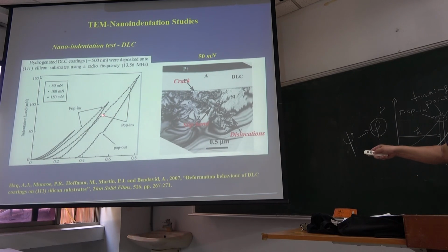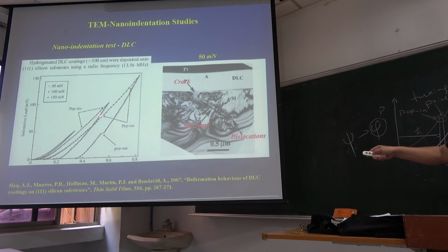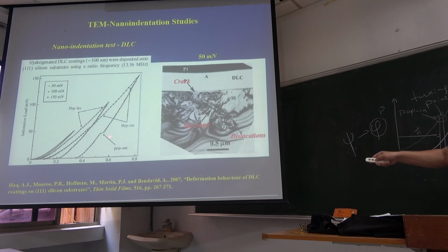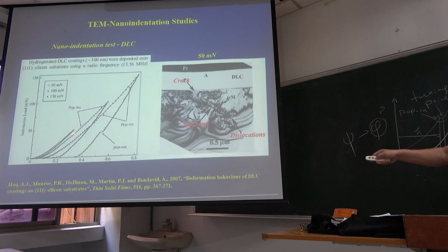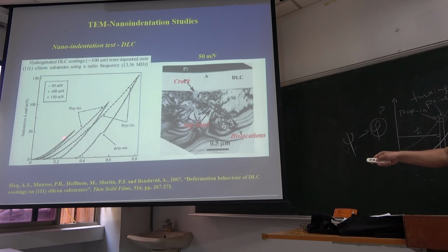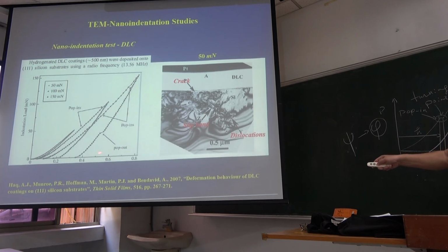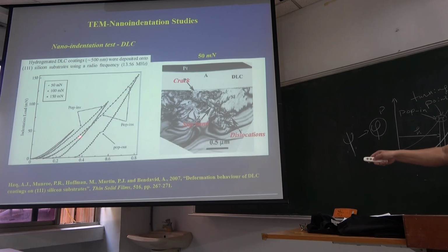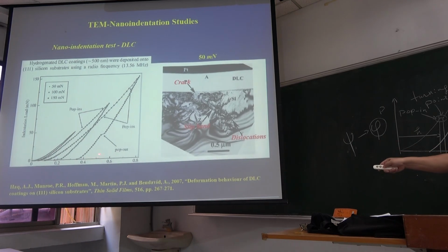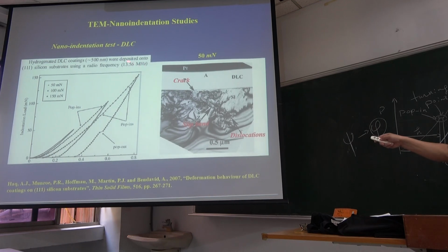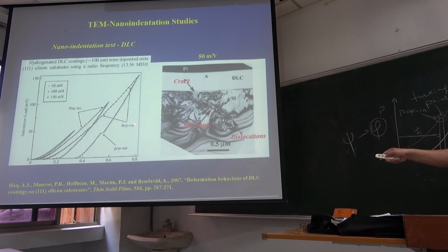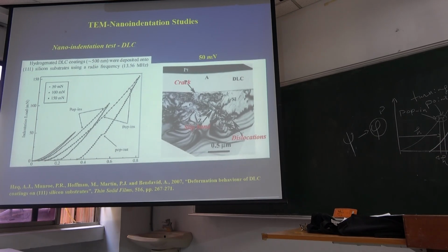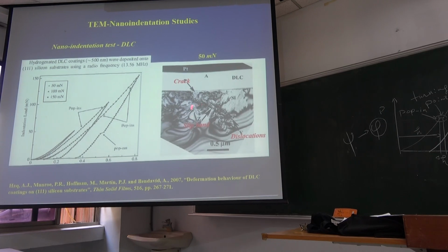Here is a pop-in, because it happens in the loading process, and here we have a pop-out. But if you change your maximum load, you cannot find the pop-in or pop-out at some maximum loads. If the maximum load is high enough, then we find some pop-in or pop-out in the loading or in the unloading process. So they have the phase change.